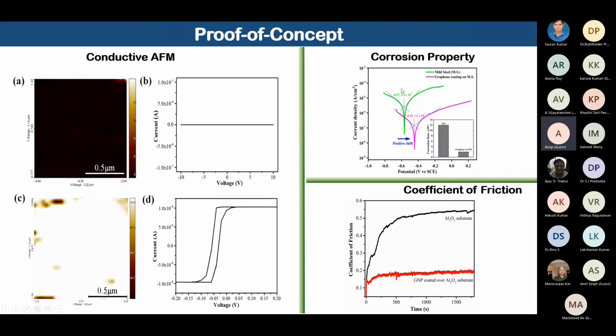Now we showed here the corrosion property of the mild steel versus the graphene coated mild steel, right? In the inset image on the right-hand side, you can see the mild steel corrosion rate is very high, but for the same mild steel, if we have coated it with graphene, the corrosion rate has drastically reduced. So it is giving a very good indication that corrosion resistance can be enhanced by just making the coating with graphene over the mild steel.